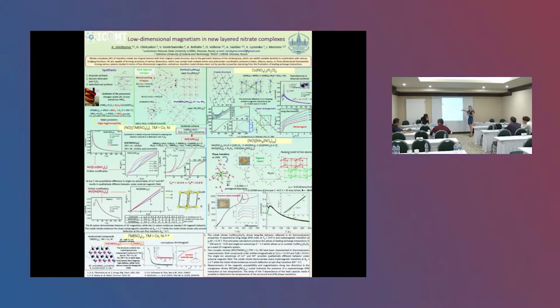This is the ab plane in the crystal structure, and this is the c axis. Like this, the Kagome layers are connected to each other. And the magnetic properties of them: there is a three-dimensional exchange. We also see phase transitions, a structural phase transition and magnetic phase transitions at lower temperature, which we can see on this slide at about 5 and 10 Kelvin. So that's all I can say about this presentation.